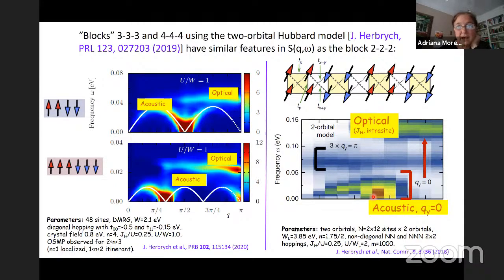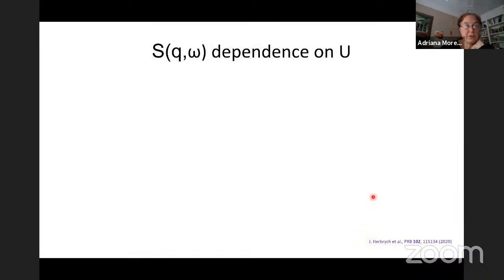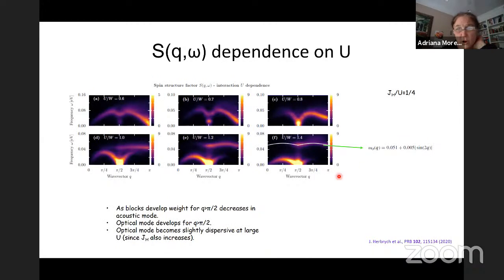So let's look a little bit more about S of Q omega and see how it depends on U. We fix J Hund over U equal to 1/4. This is for parameters with size 2 blocks. The interesting thing is to see that this is the part where the Kondo model doesn't really capture the Hubbard model. The maximum weight is at pi.